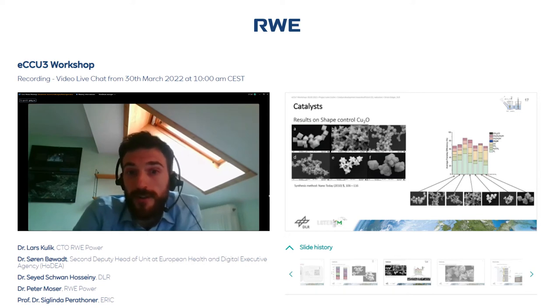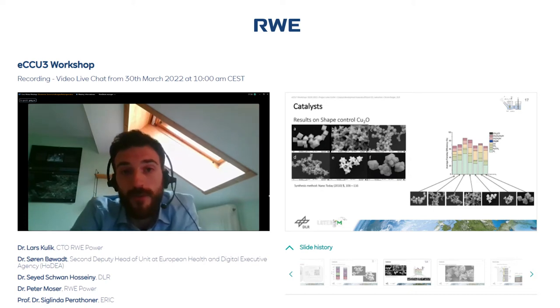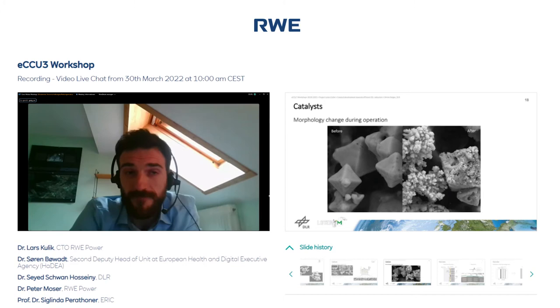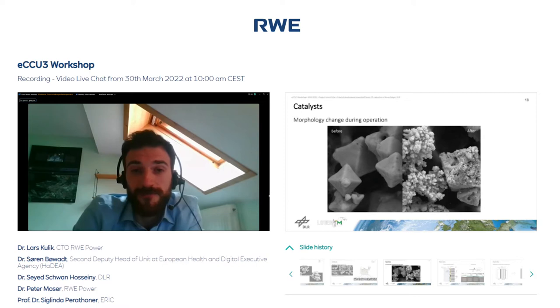And the reason for this, let's say, very similar result is that the morphology afterwards changes significantly during the CO2 reduction process. This you can see on slide 18. On the left side, there is this aqueous catalyst with the octahedra before and afterwards. You can see that there are some dendrites formed and the surface has significantly changed. So no matter with what kind of shape you start at the beginning, it will change. And this is a general problem of the whole catalytic society, let's say, for the CO2 reduction, that whatever you tailor really, your catalyst will not survive through CO2 reduction.